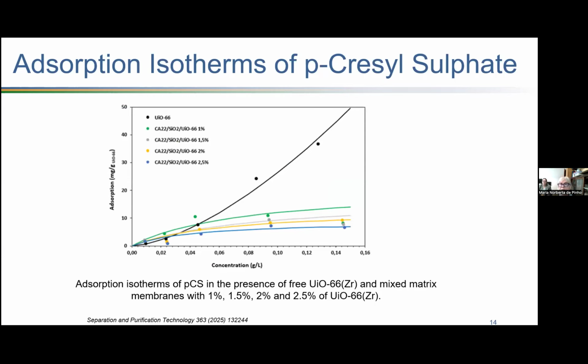And now, about the adsorption isotherms of p-cresyl and p-cresyl sulfate, as we can see here, we have the adsorption isotherms for the MOF in the free form, and then for the four membranes with the different contents of MOF. And we have a completely different adsorption pattern. We have a Freundlich isotherm for the free MOF, and then we have Langmuir isotherms for the membranes with the MOF.